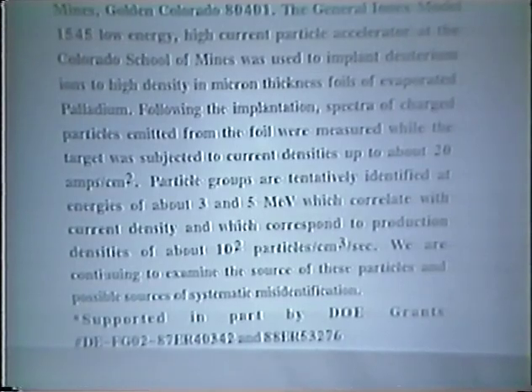We chose, rather than an electrolysis method or a gas loading method, as others have done, to use a deuterium beam to load the foil. And the reason for this is because you know the approximate range and you can get a good handle on the stoichiometry. So let me just real quickly summarize what we did.